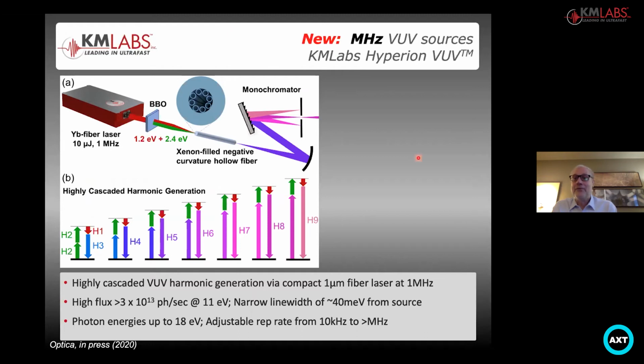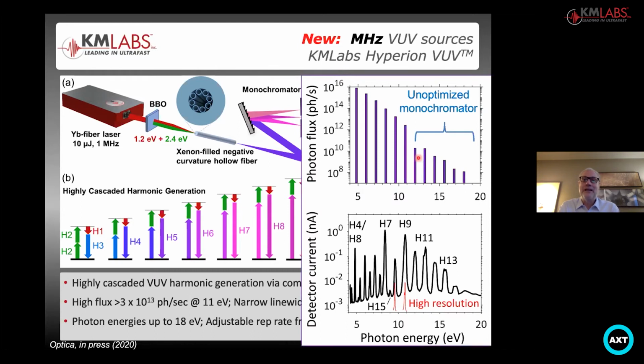Now, another emerging development is a new technology that KM Labs has developed for generating VUV light at megahertz repetition rates. This actually uses a very different setup. It's a system called the Hyperion VUV. It's a smaller system, generates light at much higher repetition rates, which is useful for avoiding space charge distortion of the energy spectrum. And it also gives very high flux over a bandwidth ranging up to about 15 to 18 eV.